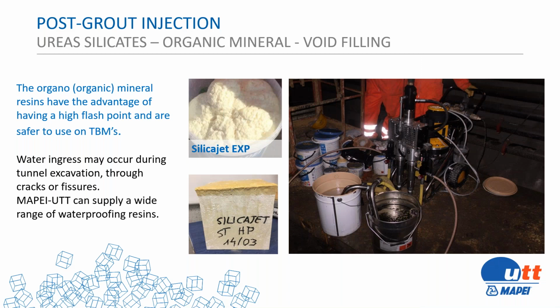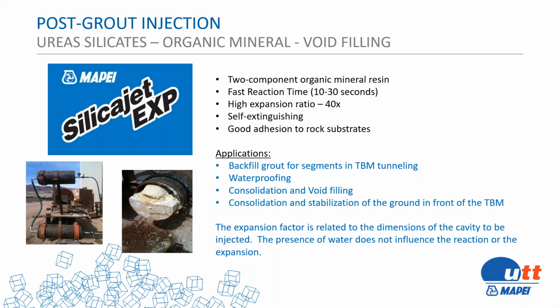We also have the silicates. The silicates are an organic mineral. And I would tell you that the silicates are probably the most used grouting material and very many different derivatives of the silicates. There's about 600 different kinds of silicates. In this case, we have what we call a urea silicate. Urea coming from the polyurea family, which would be your polyurethanes, and then the silicates. So here we have materials that can foam, can glue, and can travel very easily. Again, two component material, fast reaction.